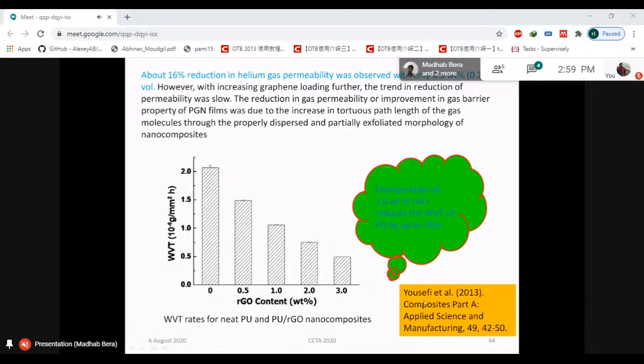In another work, Yousefi et al. investigated the water vapor transmission rate of reduced graphene oxide filled thermoplastic polyurethane nanocomposite. They found that with the incorporation of 3 weight percent reduced graphene oxide, the water vapor transmission rate of PU decreased by 76%. This barrier property, in terms of water vapor transmission and gas, is very important when we try to utilize these composite materials in certain coating applications.